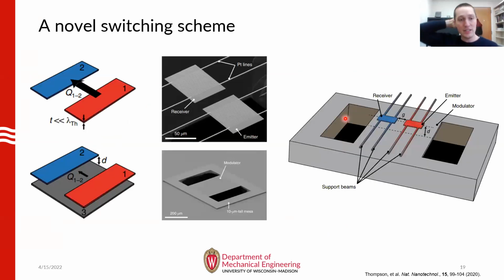Now, these insights actually gave me an interesting idea for a follow-up study where you can achieve a radiative thermal switching using these nanomembranes. So the approach relied on introducing a third nanomembrane to the system, which is parallel to but vertically offset from the emitter and the receiver by some vertical gap, which I'll call D. So I found that by reducing this vertical offset, I could actually suppress the radiative conductance between the emitter and the receiver. So this is not expected based on a naive understanding of Planck's law, because essentially the geometrical view factor between the emitter and the receiver isn't modified at all by the presence of this third nanomembrane.